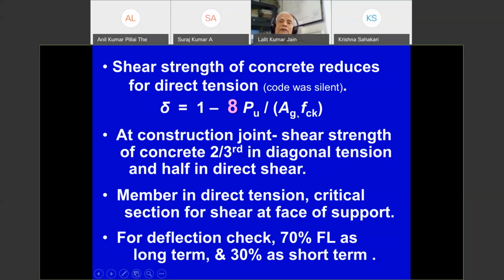Now we have construction joints in the tank, and we know that a construction joint introduces weakness, but folks, we are not talking of only the weakness. The shear strength is reduced at the construction joint, so we can assume that it can be 1/3. Of course, the reduction cannot be a sacrosanct figure, but some guidelines are to be given. The shear strength reduction depends upon the time gap between the two concrete phases and the roughness of the interface. So it can't be a sacrosanct figure, but in most cases, if you have done the construction joint well and the time lag is not more than 24 hours, you can take about 1/3 as the reduction in diagonal tension strength. Sorry, 2/3 in diagonal tension and half in direct shear.